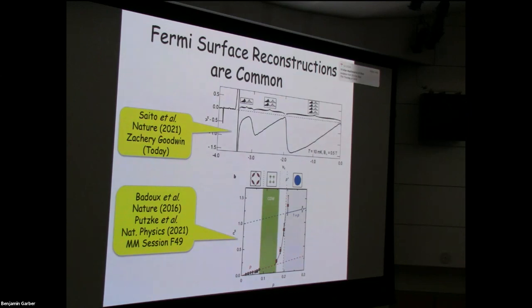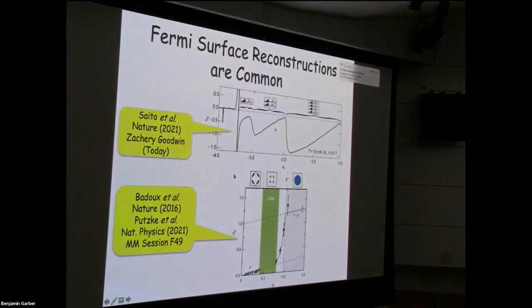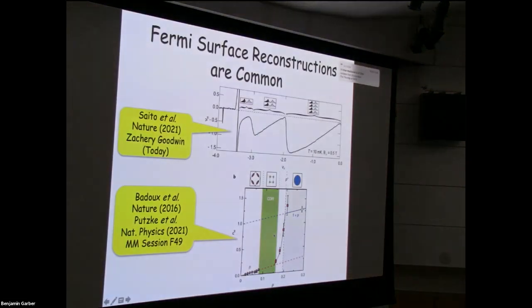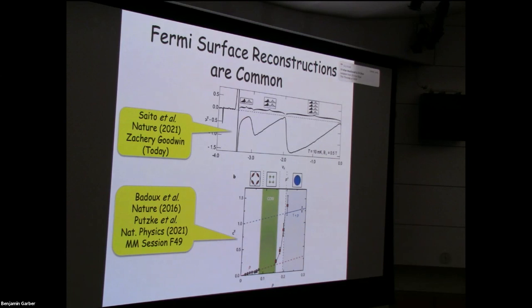And what we think is going on there is indicated by this cartoon: instead of having four flavors that you're emptying, in this broken symmetry state you completely empty two of the four flavors. That's in the broken symmetry, some kind of strong ferromagnetism. And then what you're seeing is the remaining flavors empty. And when I prepared this slide, I showed this actually in my seminar talk last week, saying that there are claims in the literature of similar things in cuprate high temperature superconductors. Steve says he doesn't entirely believe this data in the cuprates, but